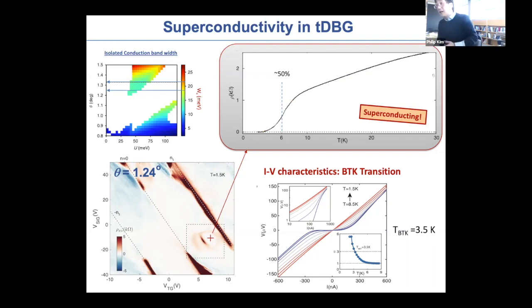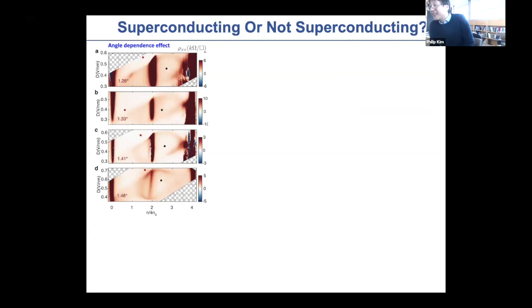So, following very similar footsteps to what has been shown in the magic angle twisted bilayer, maybe many of these twisted bilayer systems also show this correlated insulating behavior, and upon doping this correlated insulator, you may see superconducting-like behavior. Now, that's the exciting part, but here comes the experimentalist's nightmare, right? We start to explore this system with slightly different angles. And one of the motivations I mentioned is that with different angles, in principle we can tune the displacement field to bring the flat band into a reasonable distribution of the angle.